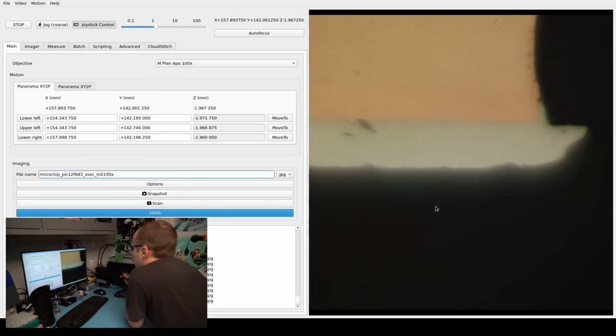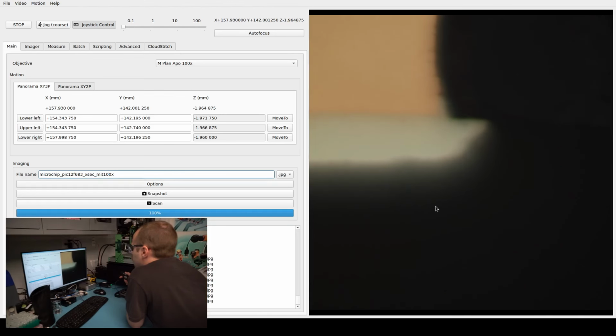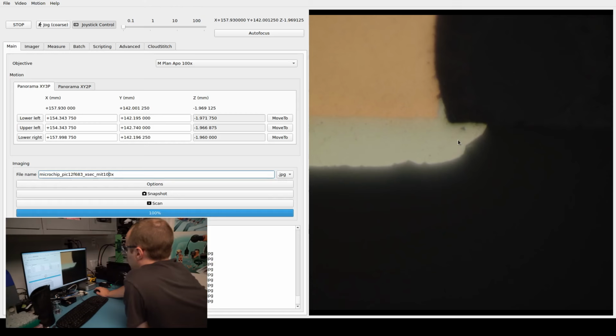And now going down to the bottom right corner of the thermal pad, we can see that the plating is actually extending out a little bit over the molding compound. So this is interesting. It means that the unplated paddle was first attached to the mold, and then after the mold was applied, then it was plated.